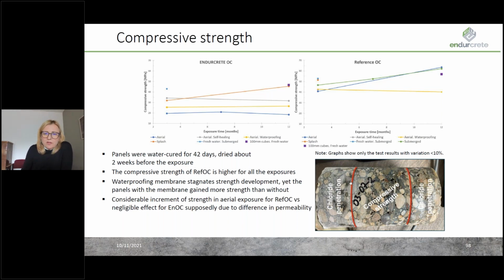The panels were used for drilling cores, and as you can see on the core here, the chloride penetration tests were performed on both sides, and then the middle core was used for the concrete compressive strength determination. Generally, we can see that the reference concrete had higher values than the EnDurCrete offshore concrete. As I mentioned before, probably unfair competition with 52.5.